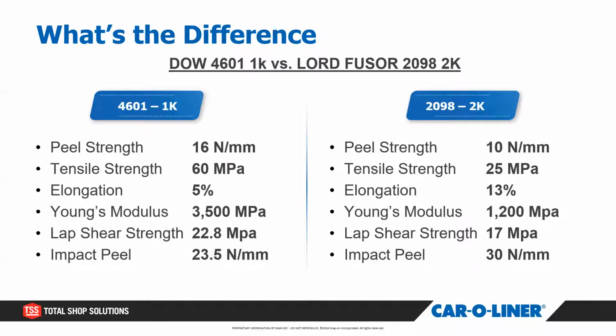But when you start looking at other things, the peel strength is very similar. The lap shear strength is very similar. But if you look at the impact peel, the impact peel is much higher on the 2K adhesives. Another thing too, when you look at these different adhesives, the 2Ks are not as strong, but because the impact peel is higher, that does help manage the joint, the energy when the impact happens.